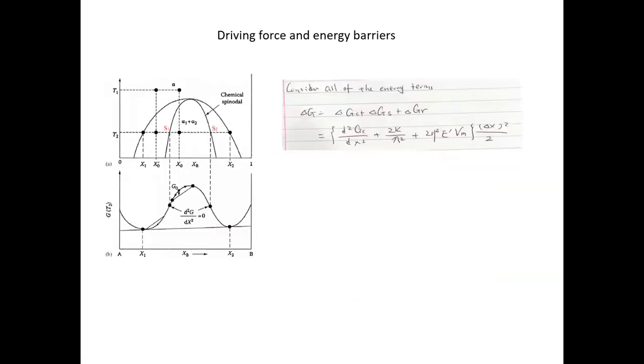So putting all of this together, we have the driving force, which is delta G_C. We have the contribution from the interface, delta G gamma, which we already derived as this. And then we have the barrier from the possible strain energy, which is given by this. We were able to formulate all of these energy terms and barriers in the form of delta X, which is the initial fluctuation, the deviation of the composition from your initial composition. Considering all of these terms together, we have the overall free energy difference for all compositions, which is given by this.